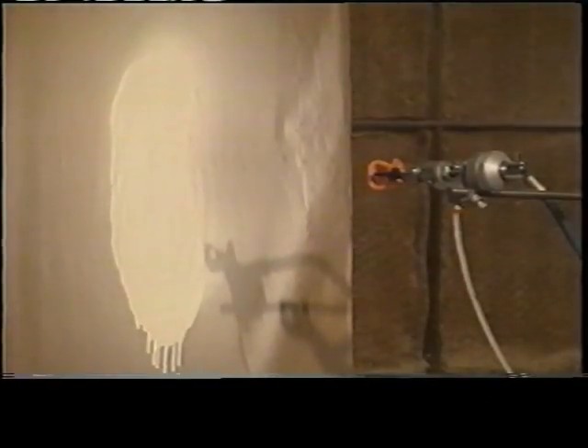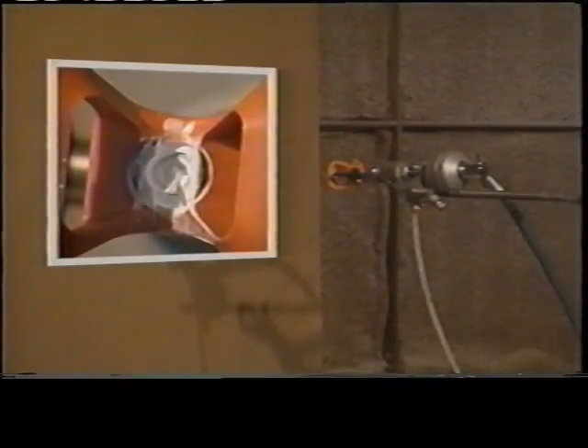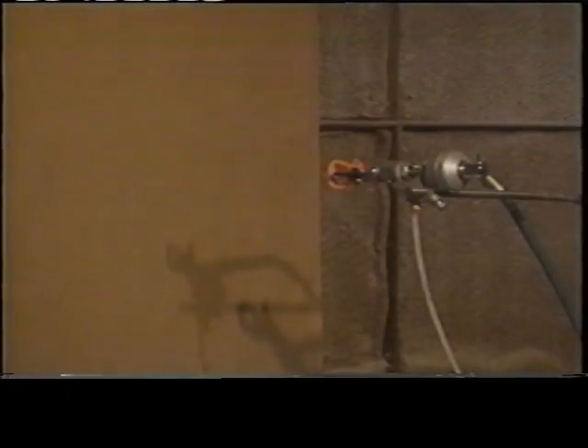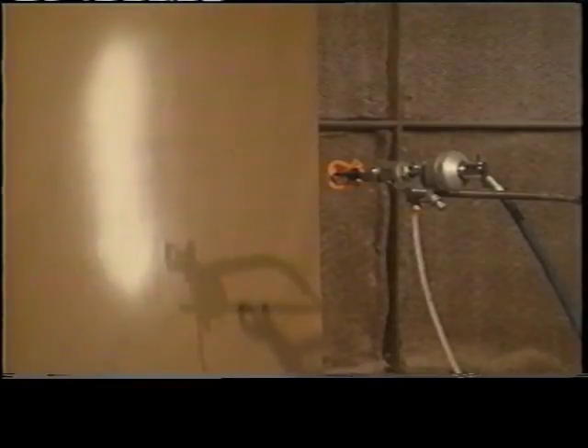Graco tested both an airless gun and an air-assisted airless unit in the automatic line simulation. Both pieces of equipment were able to apply the coating successfully. In both instances, buildup occurred on the applicator tip. However, this buildup did not affect the spray pattern.